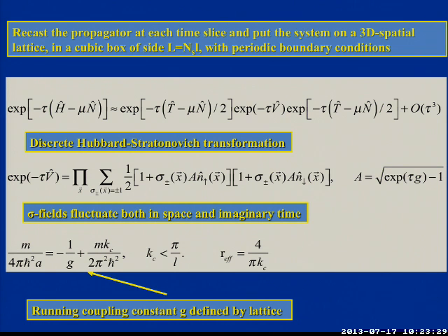If you took the experiments and the actual length scales, since they're finite systems, would that correction be small in the experiment? In the experiment, let me try to give you some parameters. The radius of the interaction between two atoms is the so-called Van der Waals radius, which is of the order of 30 to 60 angstroms, depending on the atoms. I don't remember what's for lithium-6, but it's somewhere in that ballpark. Interparticle distance separation between these systems is of the order of 3,000 to 6,000 angstroms. So that's the other one.